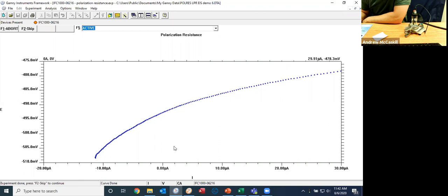You want to take data relative to this OCP value that we're looking at, because the RP value you're looking for is just a way for you to get that I corr value. You cannot measure I corr directly. There's no technique to do that. Some people would say, well, if you're measuring the open circuit potential, there's no current flowing right there, so should I corr be 0 amps? That's not the case. It can't be measured with a potentiostat.